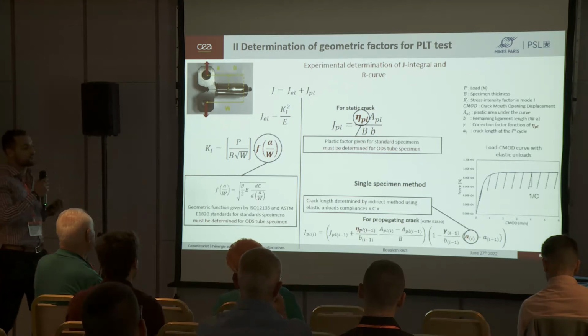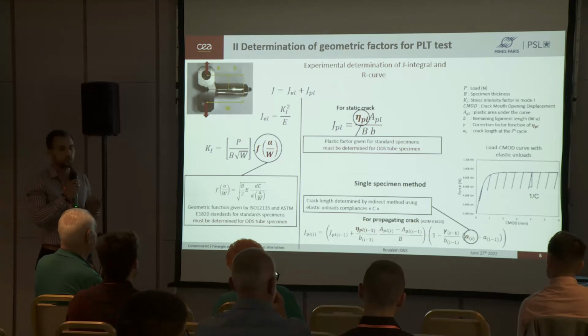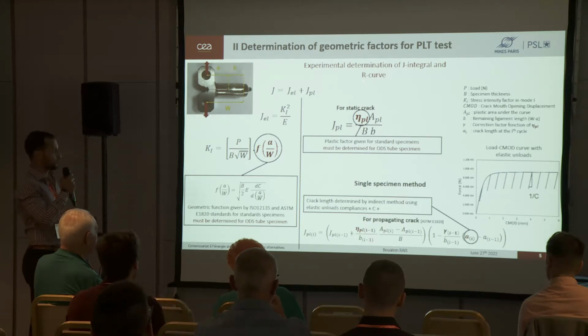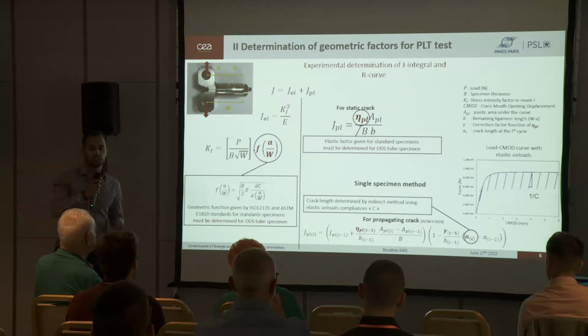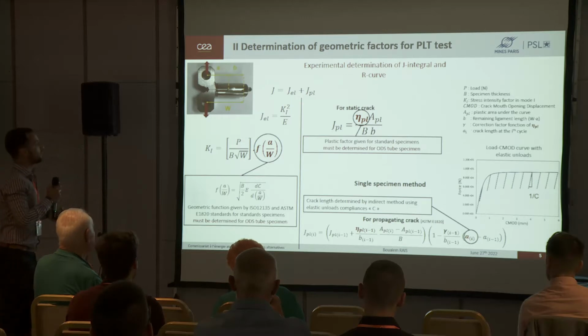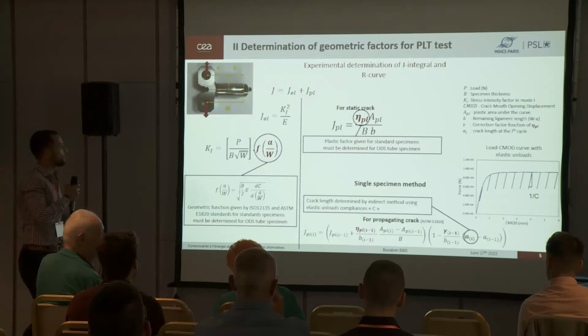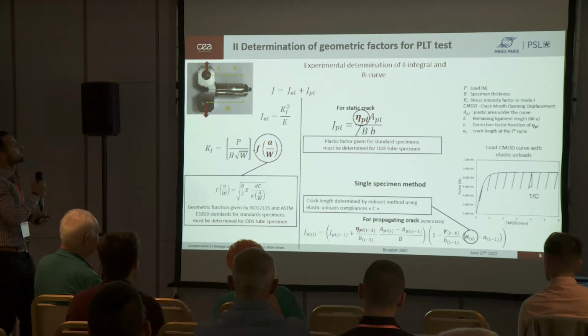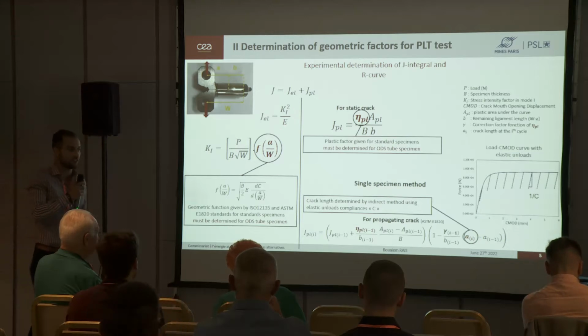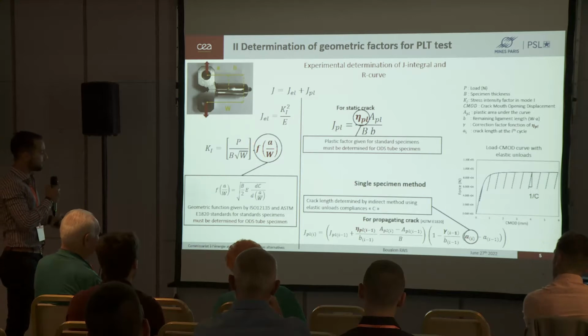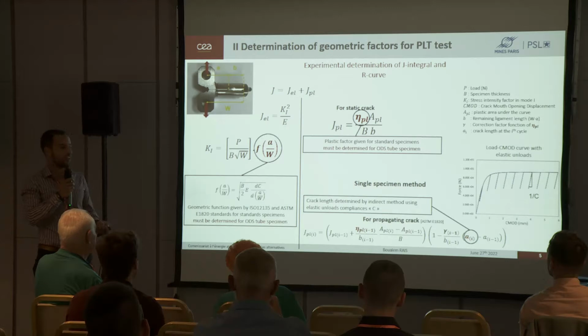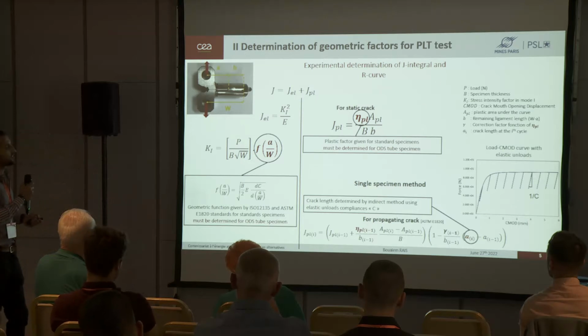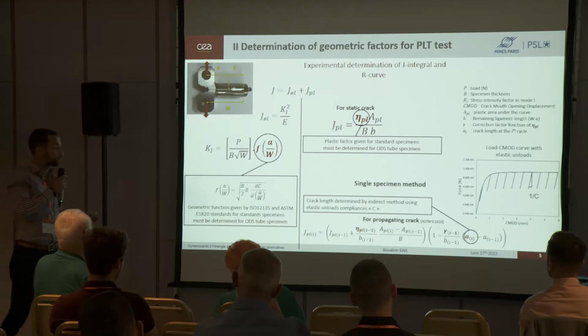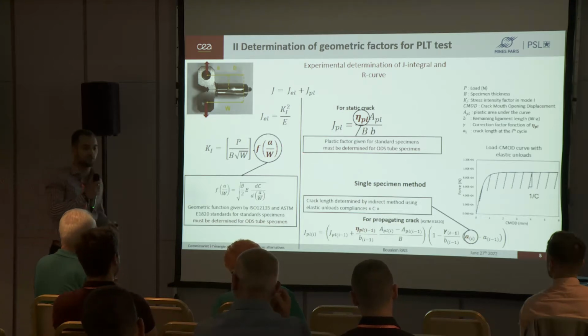To assess the toughness of materials with a certain ductility and presenting a stable crack propagation, we determine the J integral and establish the resistance curve, which is the plot of this J integral as a function of the crack extension. The J integral is the addition of two terms, an elastic one and a plastic one. For the elastic J, this part depends on the stress intensity factor that depends on this geometric function noted F, which is given by standards for normalized specimens, but has to be defined for our PLT specimens. For the plastic J, it depends on this plastic factor noted eta PL. Now, this plastic factor, like F, is geometry dependent and has to be defined for our PLT specimen.